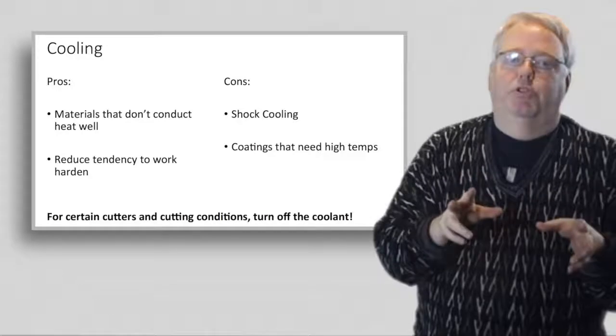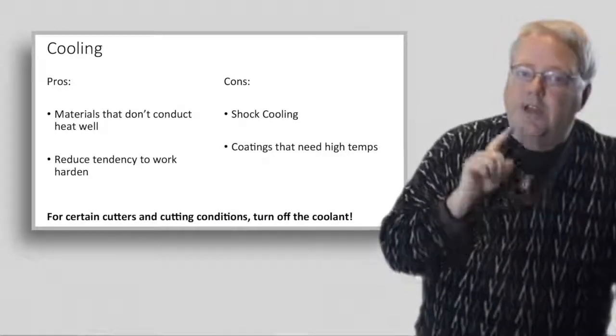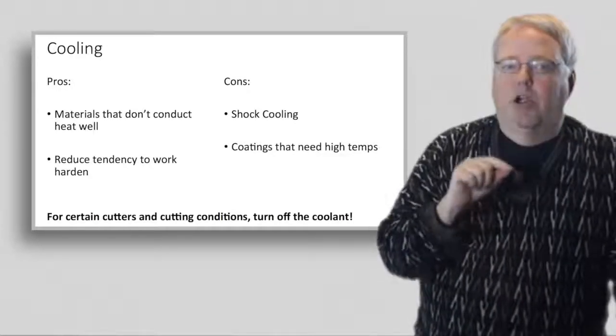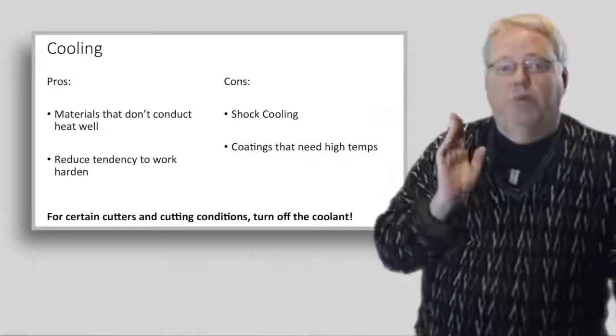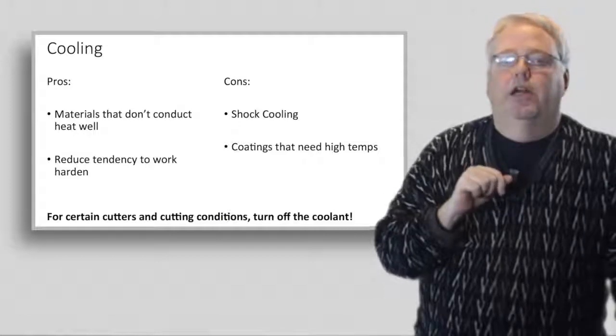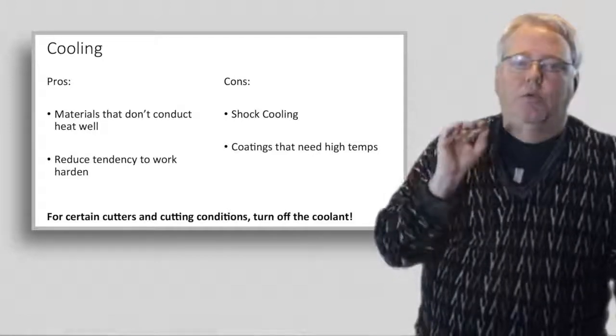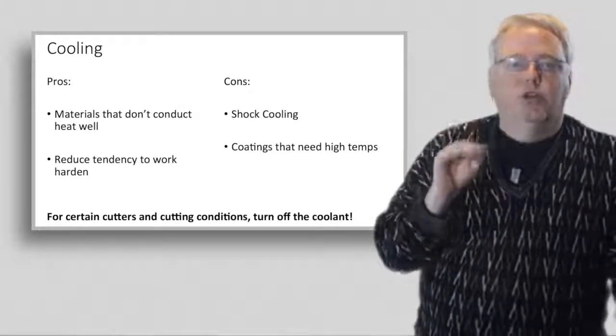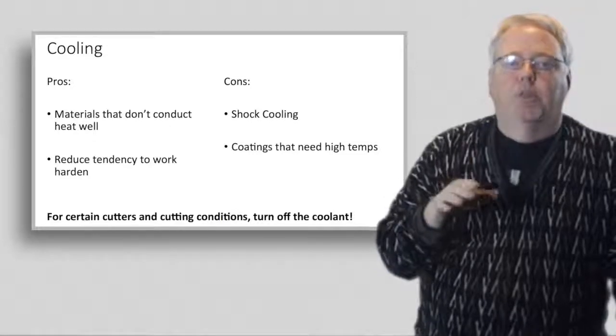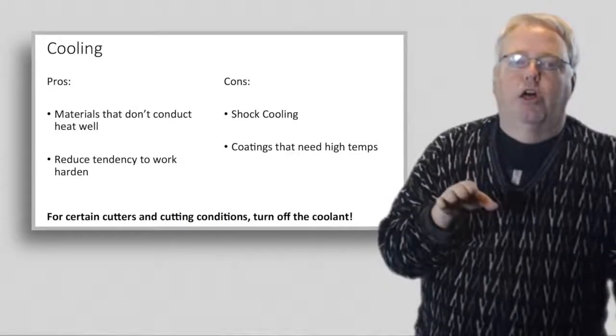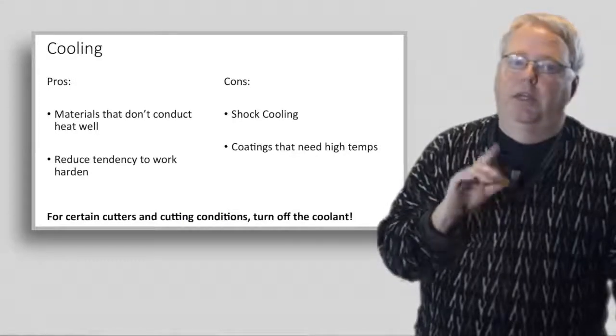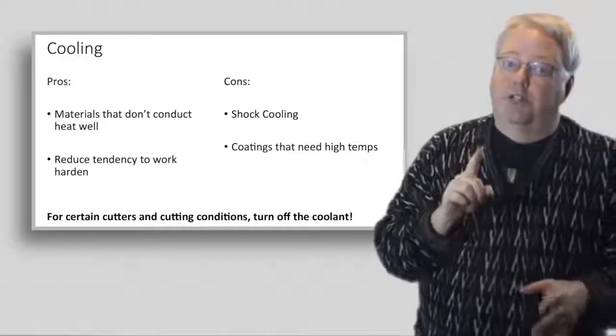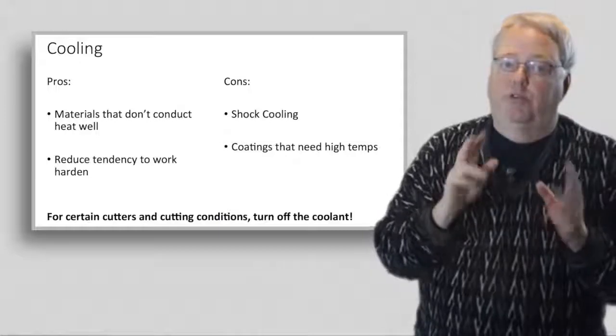Here's another negative: certain coatings require fairly high temperatures to activate and reach their full potency. Titanium aluminum nitride is a great example. With these kinds of coatings, coolant can keep them from reaching their operating temperature, which means shorter tool life and likely slower feeds and speeds. Again, check with the manufacturer to understand whether their coating should be used with coolant.